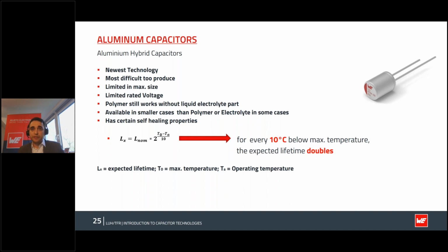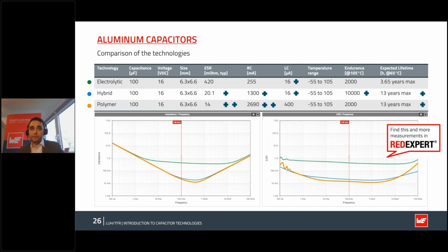So on the next slide here, I compare the three technologies with one another. They all have the same capacitance, voltage, and size. But you see the ESR for the electrolytic with 420 milliohm is not quite as good as, for example, the polymer with 14. But the hybrid gets really close to the polymer here. Same as for the current capability, you see electrolytic with 255 milliampere quite poor. The hybrid is quite good and the polymer is still the best here.